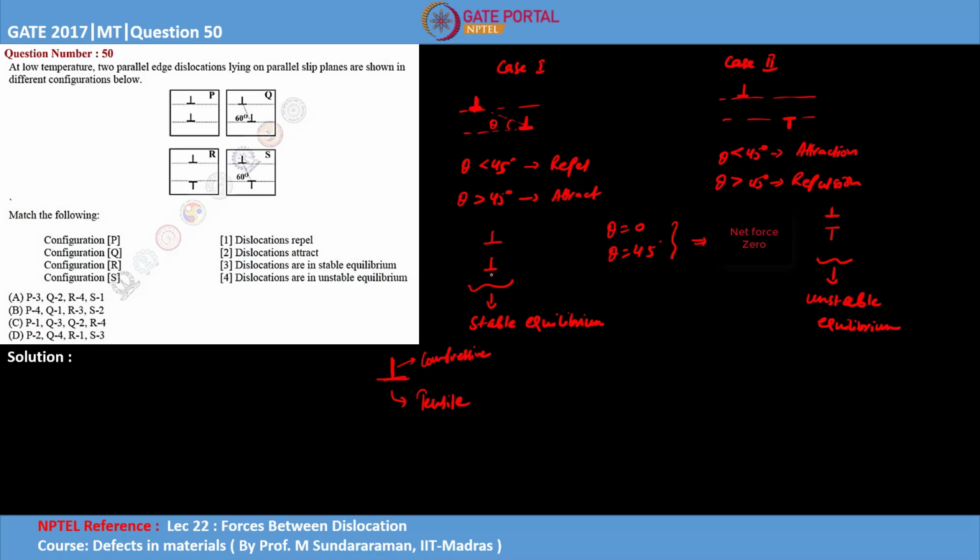So equilibrium is due to what? The forces between dislocations are zero, but depending on the orientation of the extra half plane, it will be decided whether they are in a stable equilibrium or unstable equilibrium. Now we'll answer this problem.